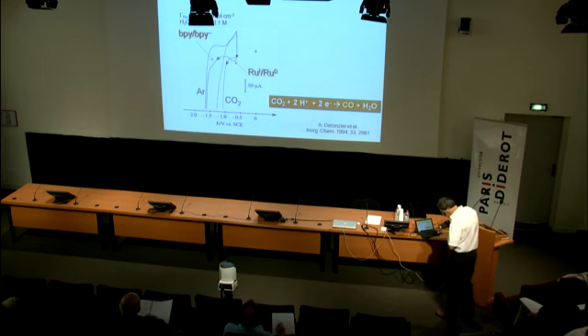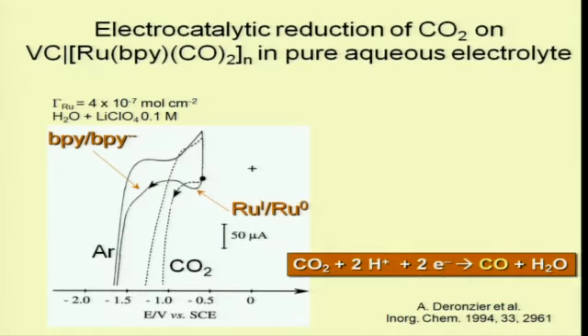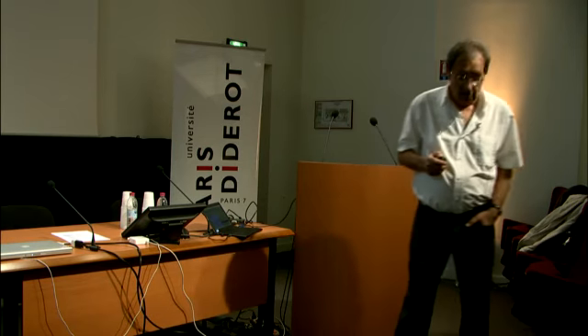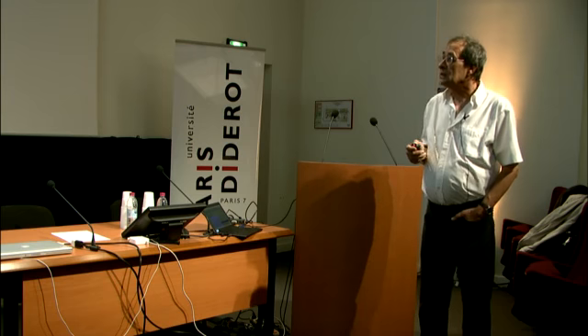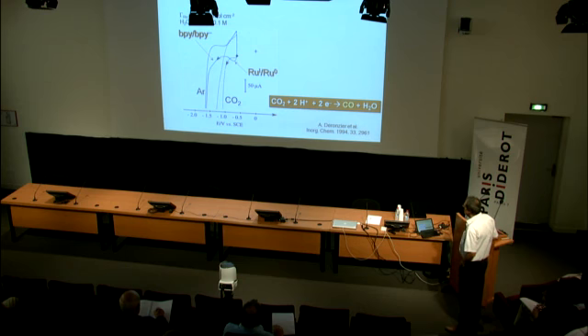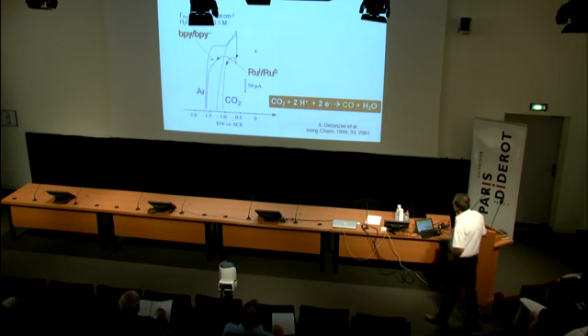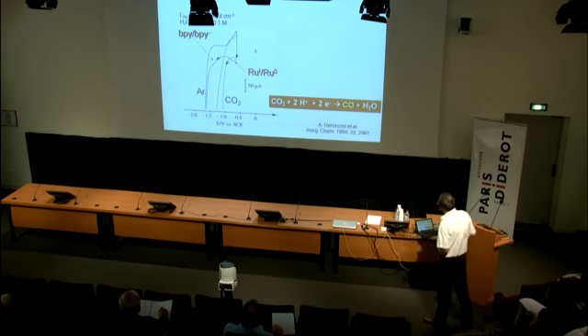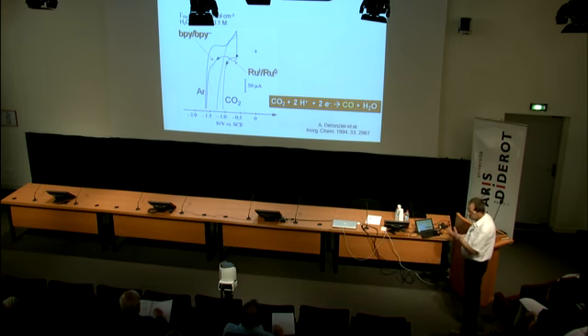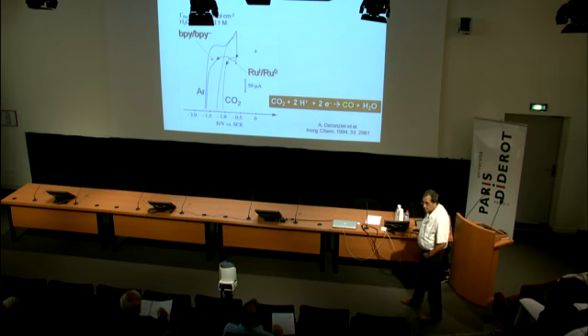So let me go to the catalytic aspect of the work. As I said at the beginning, if you want to make a nice system, it's necessary to work in a pure aqueous solution. So here is a typical signal of the film in a pure aqueous electrolyte. The electrochemical response is quite similar to what was observed in acetonitrile. That's the oxidation of the metal and reduction of the bipyridine. It's under argon.